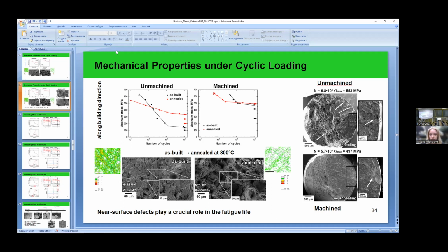We didn't make an additional investigation, but according to the literature, it's because of the near surface effect, when particles are involved in the solid parts. It's one of the reasons, and the second reason is the second scanning track, which is usually added to increase the accuracy and decrease the roughness of the material. So there is a specific scanning strategy applied to this near surface zone. So you applied contour scanning, you mean? In our case, we applied, yes.